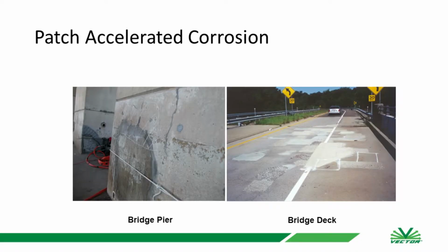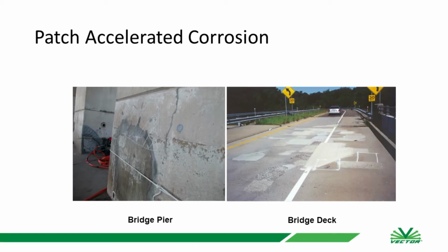Patch accelerated corrosion, or halo effect, ring effect. I don't know if a lot of you are familiar with this, but when you're looking in terms of corrosive activity, say we had a patch right here, and then the next thing you know, you have a patch that's starting next to it, and next to it, and next to it, and so on and so forth. Well, what's happening is when you're doing your patch repair, you could be doing everything correctly, right? You're milling down, or you're taking out the bad concrete, you're putting in a good material, it's bonded well, all those things. What happens is essentially you passivate the steel in that patched area.